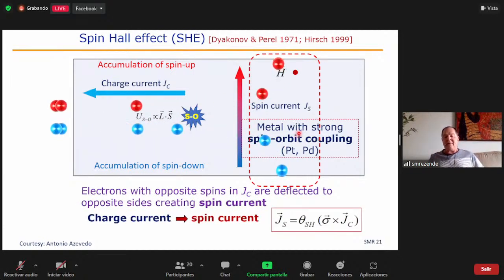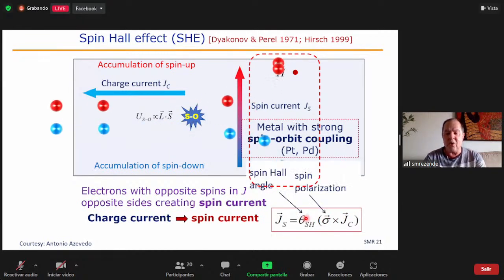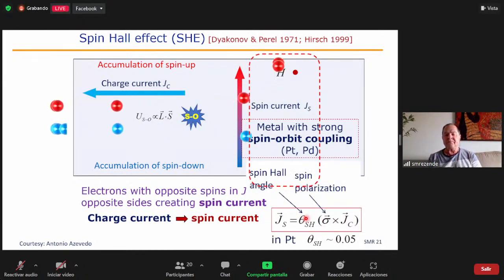The spin current can be represented by a spin current density. It's proportional to the charge current, and it's perpendicular to the two. It's represented by this cross product here, sigma cross J, and theta is a parameter that says how strong the effect is. In platinum, the spin Hall parameter is 0.05, which means 5%. There are materials that we know today that have 50%. In other words, half of the electrons in the current are deflected to produce a spin current.